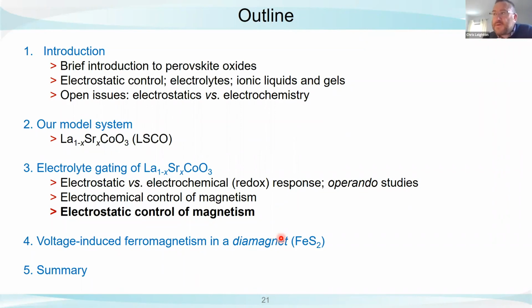And we actually published this. I'd be happy to show you if you like. It's got nothing to do with magnetism, but we did go through the thought process. If we're right in that thinking, are there oxides where we can basically completely eliminate this effect because the diffusivity is tiny? And there are. One that we found is barium tin oxide, a perovskite that has about 10 orders of magnitude lower oxygen diffusivity at room temperature. We did experiments on that, and it is entirely electrostatic. We can see no electrochemical effects whatsoever. They really seem to be totally shut off. So that's our view of why the cobaltites have generated so much interest in this vein. Okay, thank you. Yeah, thanks.